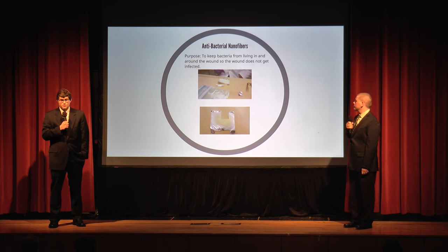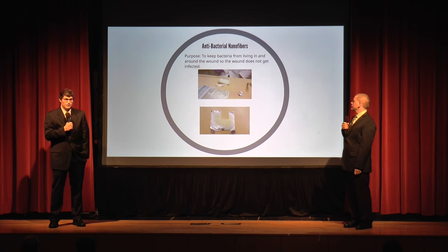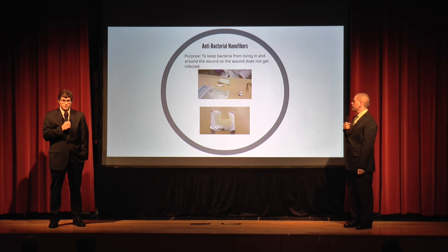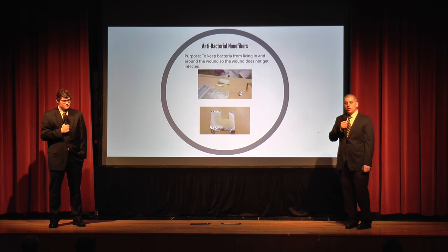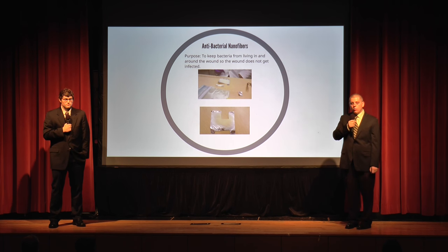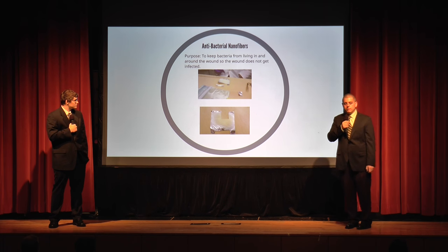Antibacterial nanofibers keep the wound from becoming infected. Our fibers were comprised of PVA and a very small concentration of silver nitrate. Silver nitrate can be harmful to the body in large concentrations. Therefore, we utilized 0.01% silver nitrate in all of our solutions. This concentration was deemed safe by many research papers.